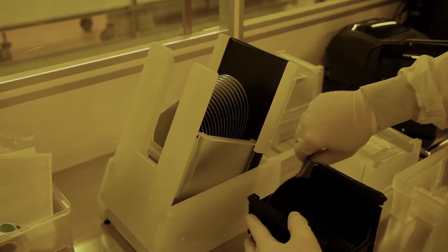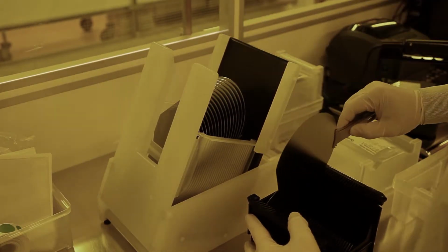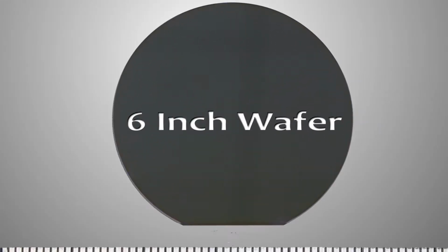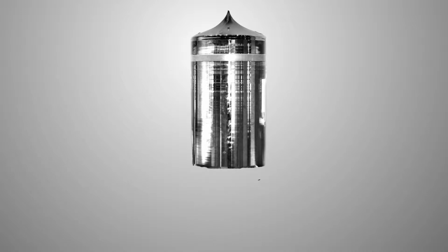Remarkably, if you were to watch for materials going into the Dimatix MEMS fabrication or fab, the only raw component you would find would be 6-inch diameter silicon wafers. Sawn from a single crystal, forged from high-purity sand, and controlled to tight thickness tolerances, these wafers are typically only 650 microns thick. That's less than 2/3 of a millimeter.